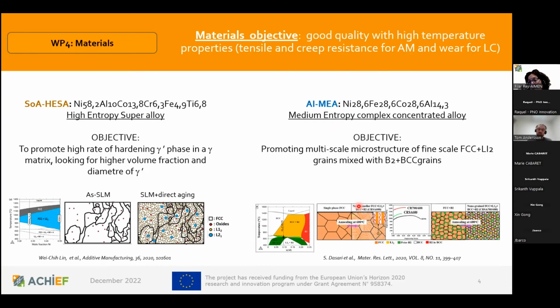So in the case of the development of the materials, we select this one that was the first that we selected, and it is a high entropy superalloy. And the second one that was selected using these digital tools, we call medium entropy because it has 4 elements. But in any case, the approach is quite different. So the objective with the high entropy superalloy is to promote the hardening with precipitate gamma prime phase with a higher volume fraction, but also with a large diameter in order to increase the resistance.